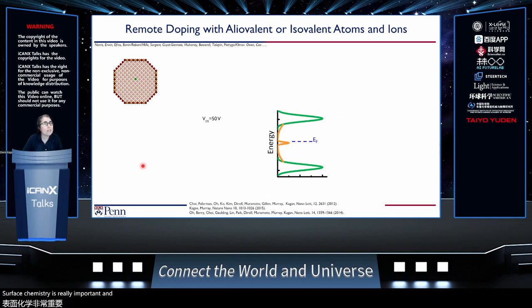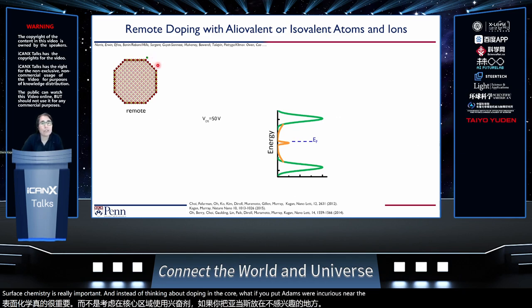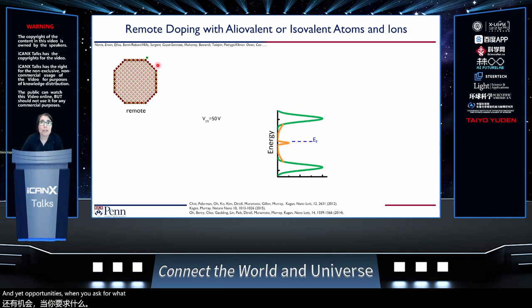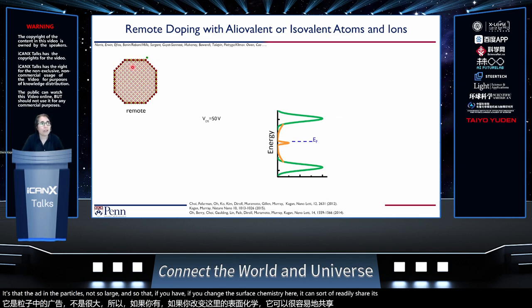And instead of thinking about doping in the core, what if you put atoms or impurities near the surface? Sometimes we refer to this as remote doping. And the opportunity is when you ask, well, what's different about a small particle? It's that the particle's not so large. And so if you change the surface chemistry here, it can readily share its electrons with the whole system.